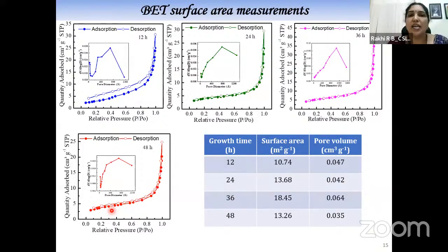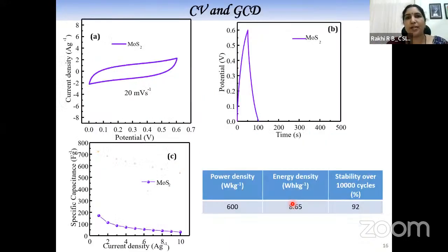Then we have done the surface area measurements. We found that almost all the samples have a small BET surface, mesoporous surface area, and the sample which is grown at 36 hours has the maximum surface area, that is 18.45 meters square per gram. Then what we have done, we didn't test the as-grown nickel foam sample directly. First, with the sample with the maximum surface area, which we expect will give the maximum supercapacitor performance, we constructed the symmetric supercapacitor the conventional way with a mass loading of 1 milligram per centimeter square.